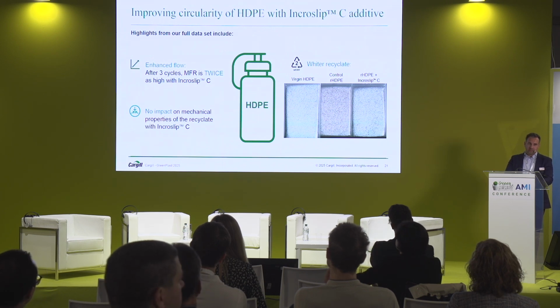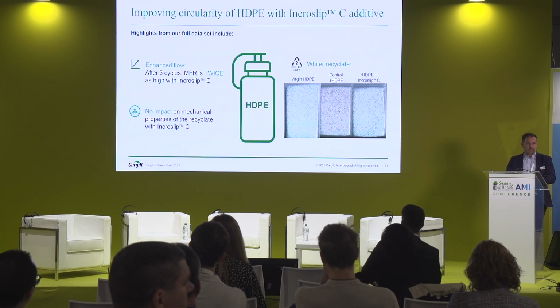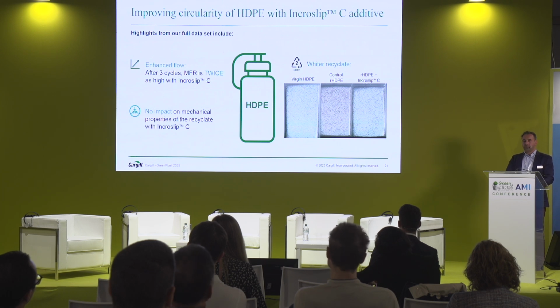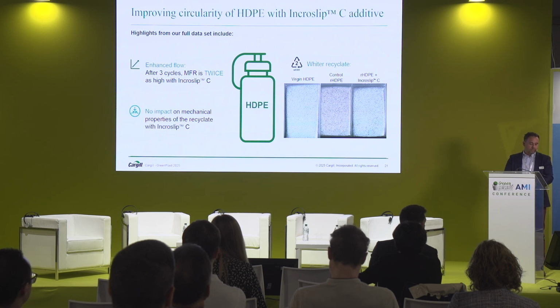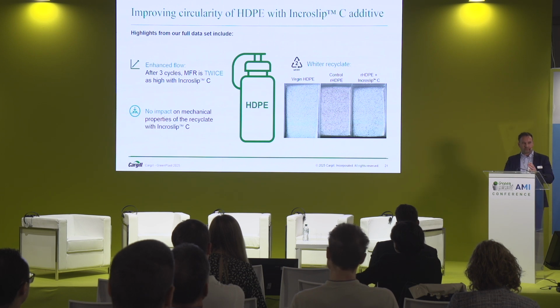As expected, we didn't see any impact on the mechanical properties. We know full well that these additives at these amounts are not plasticizers, so the mechanical properties remain the same. The color, as you can see, is better with Incroslip-C, not because the additive makes it whiter, but because the additive protects it from degradation, which is important. And we saw an increase in the MFR, the melt flow rate. After the end of the third cycle, there was a reduction in the MFR of HDPE, which is expected, typically due to cross-linking. With the additive, it was increased by 2 times, which was a great thing to see.